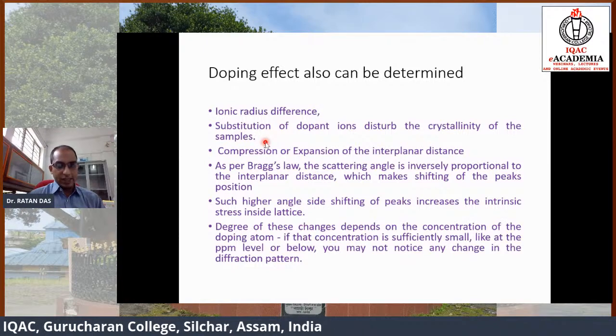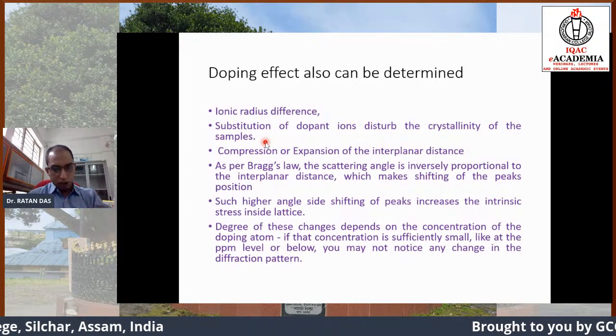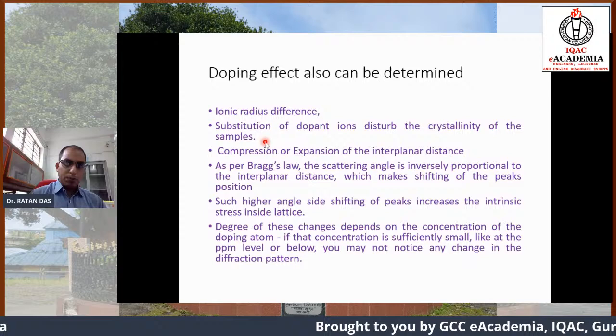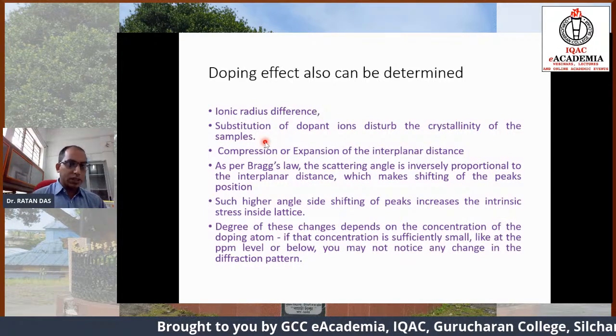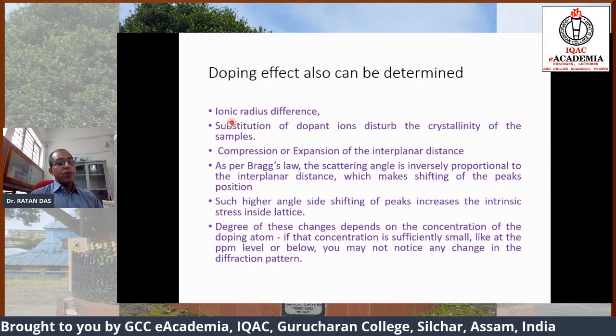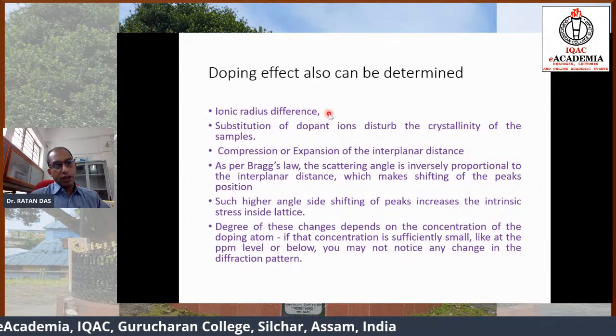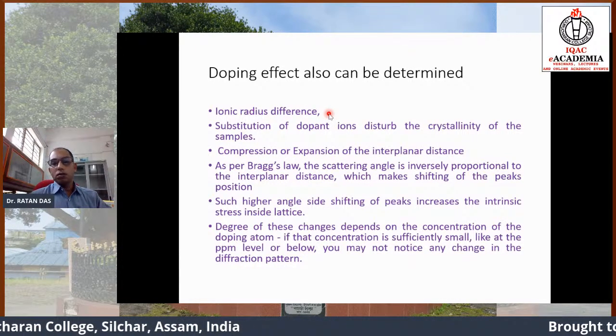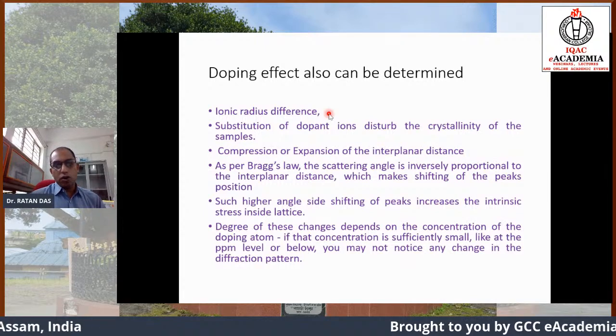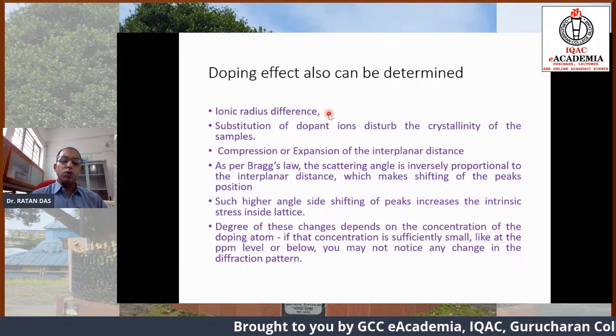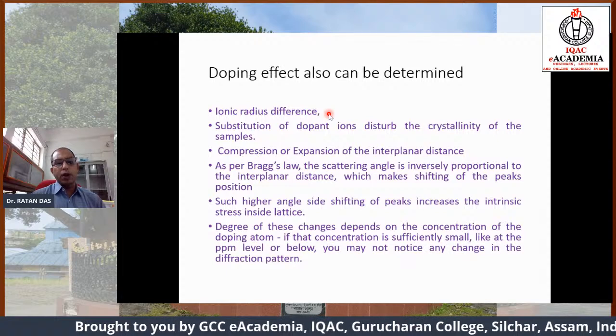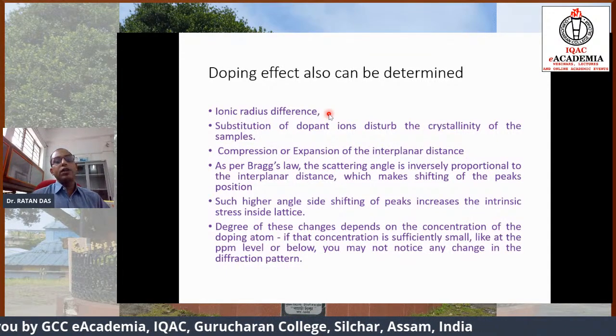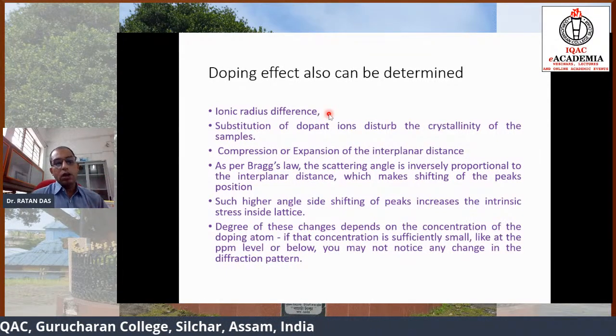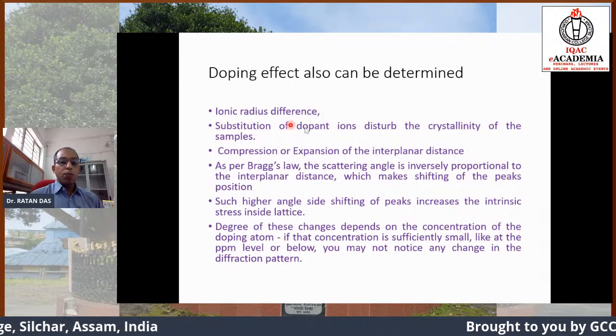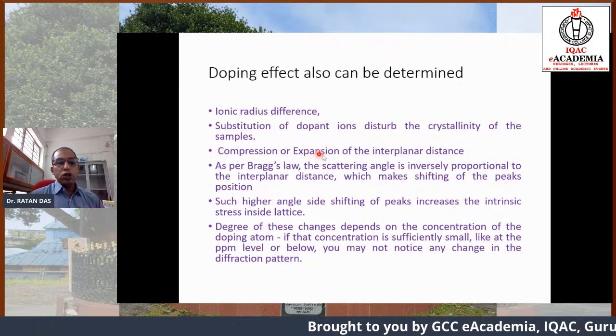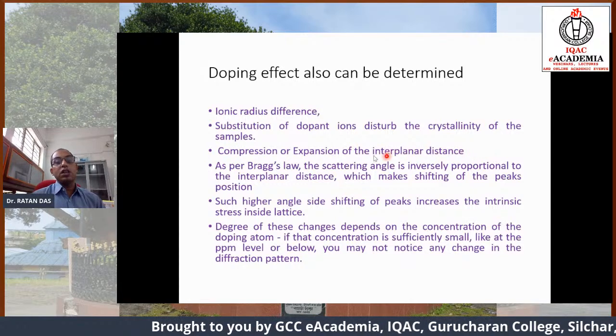Suppose we have a CdS nanocrystal. If we dope with silver, then the silver at some places will replace the Cd. So there may be ionic differences, because the ionic radius of Cd is different from the ionic radius of silver. So we may have different types of dopant, where the ionic radius may be smaller or larger than the host material. Because of the substitution, some compression or expansion of the interplanar distance takes place.